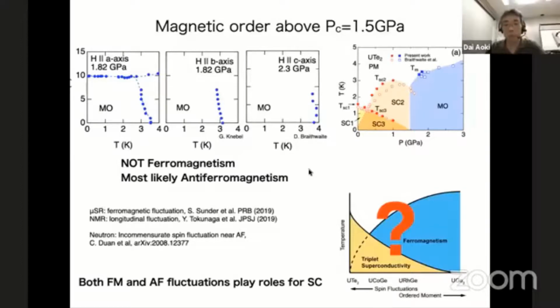And of course, ferromagnetic fluctuation is experimentally detected at ambient pressure by μSR and also NMR, by Tokunaga-san, who shows the longitudinal fluctuation. This indicates the ferromagnetic fluctuation is rather strong, at least at ambient pressure. Again at ambient pressure, very recent results appeared in arXiv showing inelastic neutron experiment results, with incommensurate spin fluctuation. These results are somehow controversial, but I believe that in this uranium ditelluride, both ferromagnetic fluctuation and antiferromagnetic fluctuation are important for superconductivity.